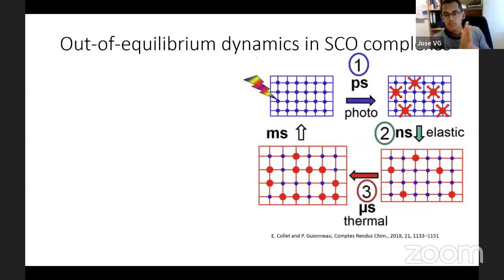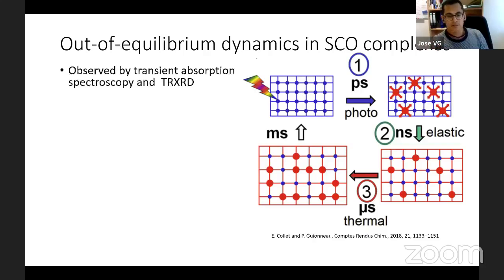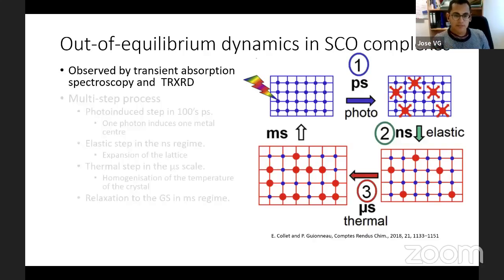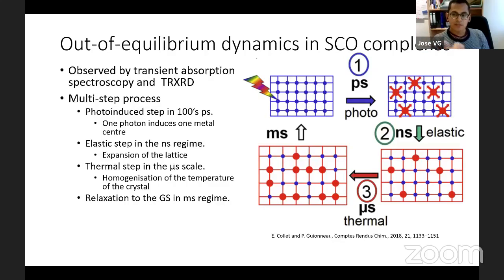When we use a single pulse to excite the spin crossover crystal, there is a very multi-step out-of-equilibrium dynamics. So when a single pulse arrives at the single crystal of the spin crossover complexes, the first thing that will happen is the light will excite some metal ions from low spin to a high spin state. And that will create one of these changes we have mentioned. First of all, the bond length will increase. And if there is enough cooperativity in the material, that could pass to the molecular rearrangement, crystal packing, or the whole crystal, right?